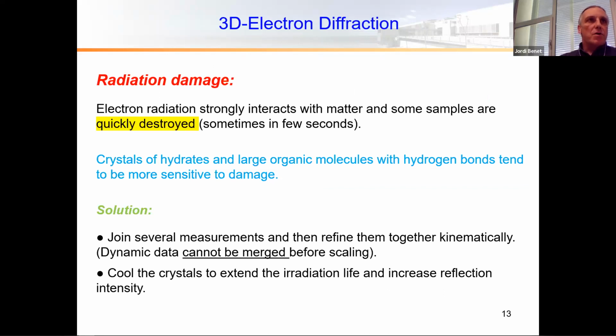Radiation damage is also an important issue with electron diffraction. In some cases, when we have diffraction with electrons, the samples are quickly destroyed, sometimes in a few seconds. And I have the feeling that especially hydrates and large organic molecules with hydrogen bonds tend to be more sensitive to damage. But I already have a solution. One way to avoid these problems is to join several measurements and then refine them together kinematically to merge the data. The only problem is that in this case, you cannot use dynamical refinements. You cannot merge data before scaling. And another way to reduce damage and increase the lifetime of the reflections is to cool the crystals.